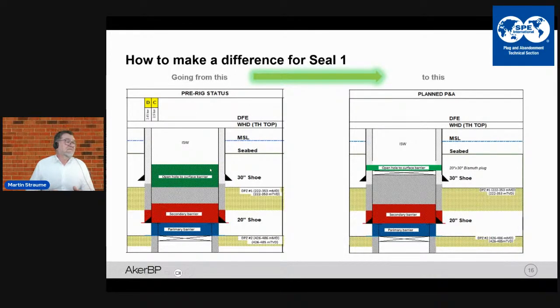And this is a picture of what made the difference for us. We started out with the green open hole to surface plug, as is normal, but we ended up milling a window out to the 30-inch to cover the D annulus and all the inside of the 20-inch surface casing with one bismuth plug and its sealing. So that was basically my story.